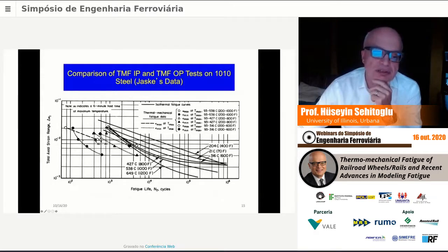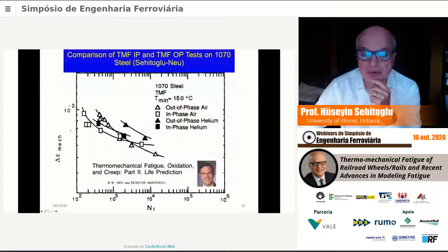Now, the thermomechanical fatigue results are shown here on the left-hand side. In almost all cases, the thermomechanical fatigue lives are much shorter than the isothermal fatigue lives. So even for cases where the maximum temperature is 538 Celsius here, which is lower than the 649. The maximum temperature in this test was 649, and here the maximum temperature was 538. And even then, the fatigue life is much shorter. And epsilon min at T max means out-of-phase loading, of course. Epsilon max at T max means in-phase loading. So this point here is an in-phase point. These points are out-of-phase points. So there seems to be a bit of a crossover here, but we're going to investigate that a little bit more.